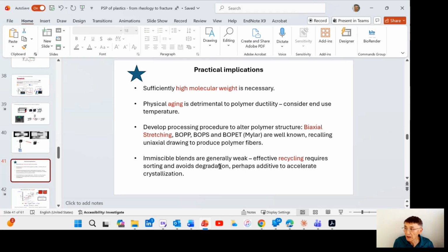plastics. And if you don't have enough compatibility, you have a phase A that builds a network because it has high enough molecular weight. You have a B that does so, but at the interface, it's a completely trivial message for anyone, including the folks who asked this question, there's nothing at the interface. If you have a compatibilizer, naturally, that compatibilizer will have to be high enough molecular weight that it can reach and entangle, in my language, forming loops, uncrossability, to preserve the continuity of the network, in absence of which you're not going to have good properties.